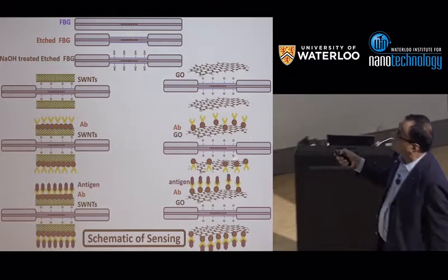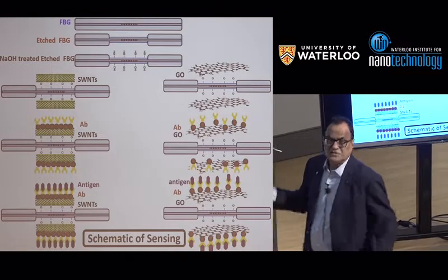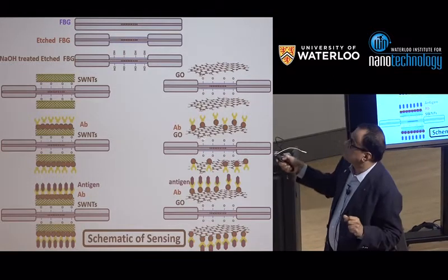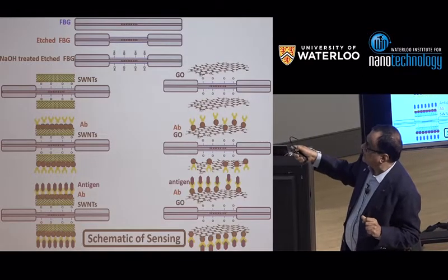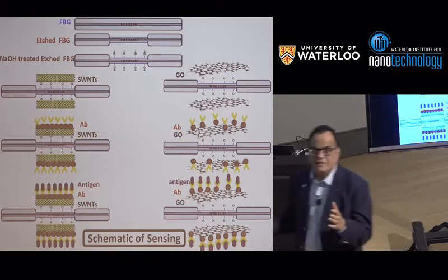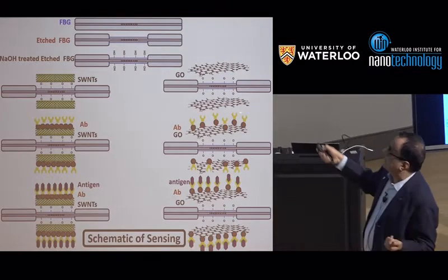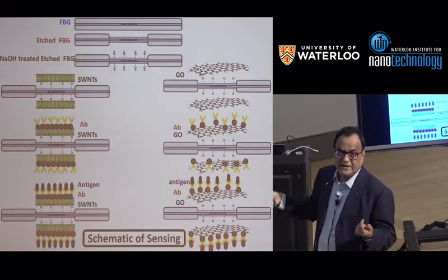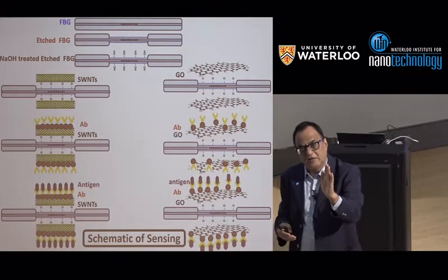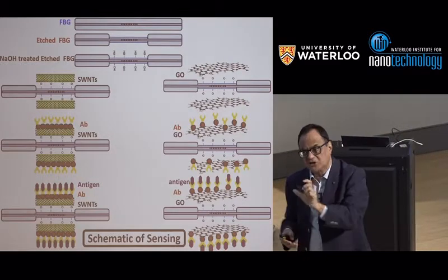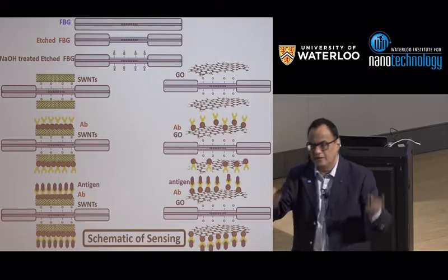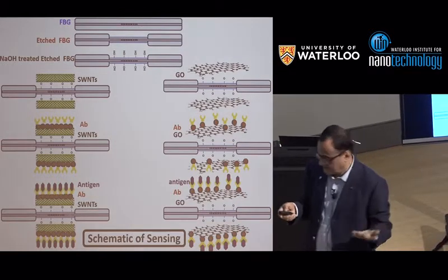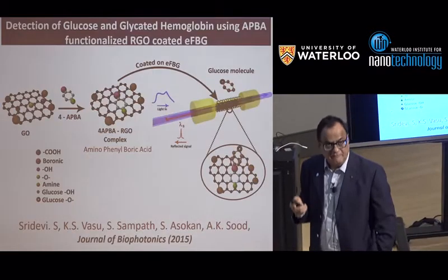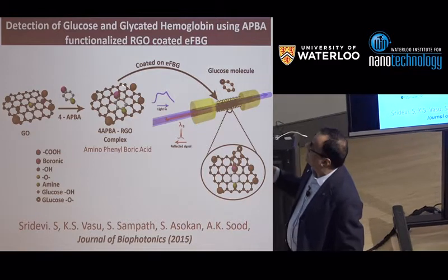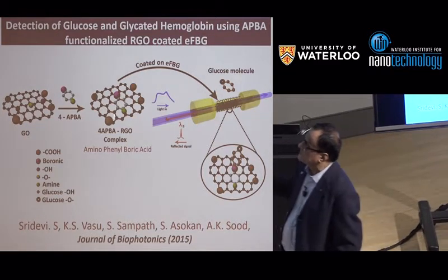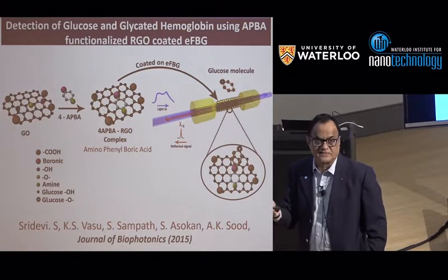If you do that, you have a material which is very sensitive to change in refractive index when something happens. So on this nanomaterial, you put the right antibodies, and then when the right antigen has to be detected, you will have this coupling and change in the effective refractive index, which will shift lambda b. So experimentally, we are measuring the change in the Bragg condition as a function of concentration of what you want to detect. So the question is, does it work? We were surprised that it is very sensitive and very specific. A few years back, 2015, now more experiments have been done. We wanted to see a glucose sensor, which is like a guinea pig.